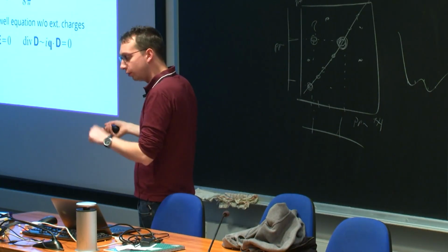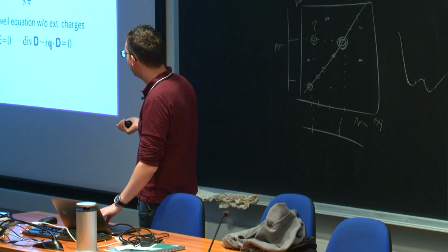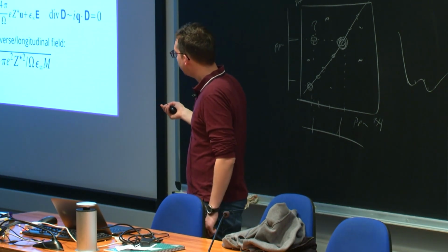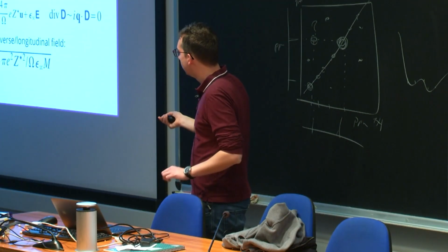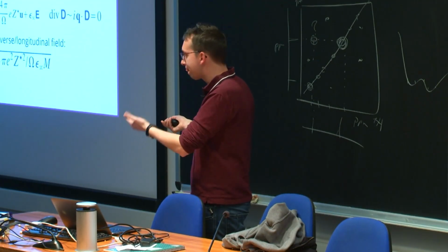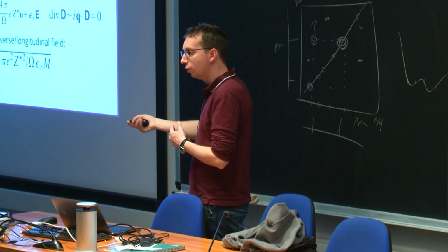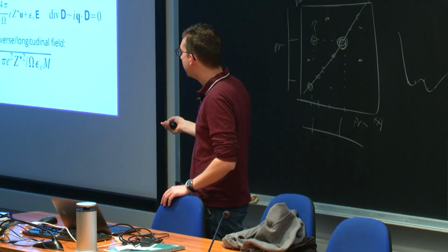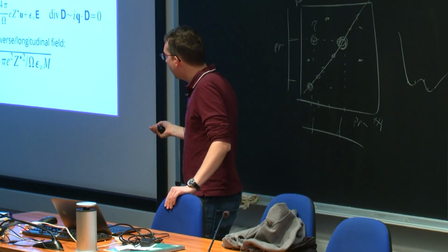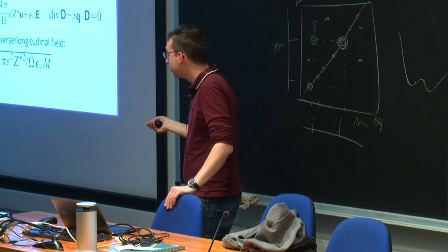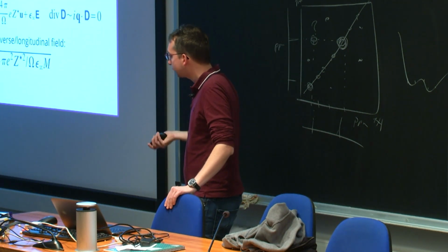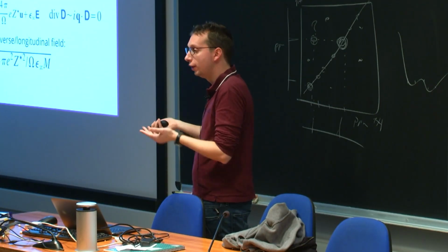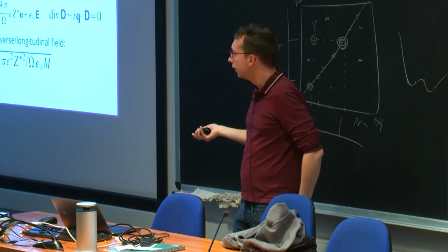So go back to your book from the second year in the university. You get the Maxwell equations and put everything together, and you can solve this system, and you get that for the longitudinal phonon, the frequency, when you include also the effect of depolarization, is the frequency of the phonon, like without this long-range interaction, plus a term which depends on the effective charges and the mass of the atom and the electric constant, and you get that the transverse frequency doesn't change, like when you move the plane of charge like this, if you don't change the distance, you don't have any polarization, so you don't get any correction.